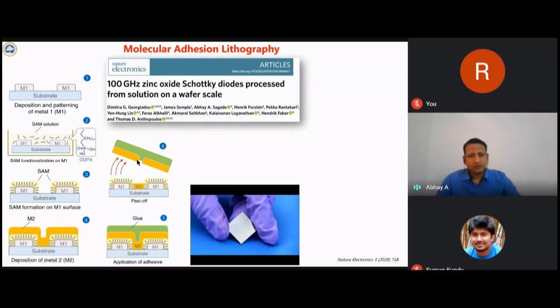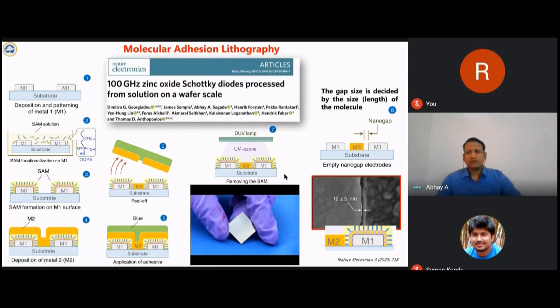This is because metal 2 is selected in such a way that it has a very poor adhesion to this SAM molecule. In the last step, you expose your chip to oxygen plasma. It will burn out all this organic layer, and you will now have a chip with metal 1 and metal 2 separated by a nano gap which has a length equal to the length of the SAM molecule used. Here is an example of aluminum and gold metal electrodes separated by this small nano channel, or gap electrode, of a size of almost 12 nanometers.